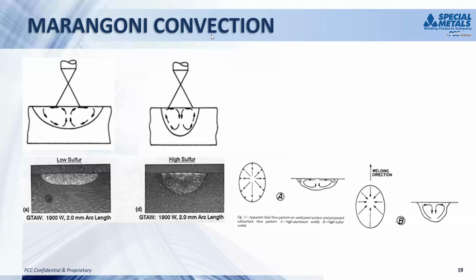And so what happens then is it causes the flow direction to be as on the right with the high sulfur, so that the superheated material directly under the tungsten is directed down, and the fluid flow comes in from the outside and then goes down. So that creates deeper penetration. In the case of the low surface active element of sulfur in the nickel alloys, the fluid flow is reversed. It flows from the middle of the surface outward. And so then the superheated metal directly under the arc flows to the outside, and it creates a wider, more shallow pool.